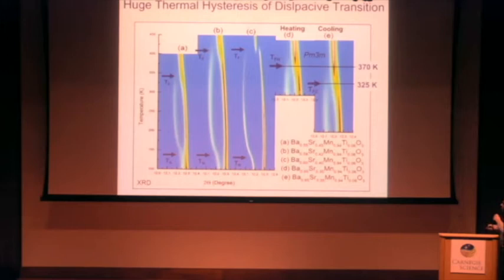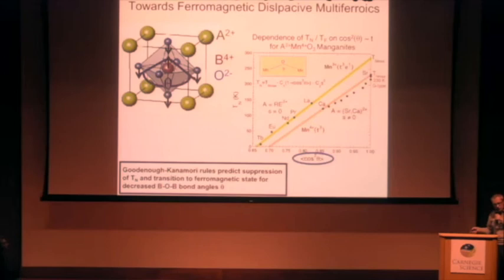Here is an example of several more X-ray diffraction experiments with many different samples. I want to point out this situation here with this composition, which we managed to measure both on heating and cooling. I want to emphasize this point: in this case, here is just cubic to tetragonal and then back to tetragonal or cubic at low temperature, so there are no three transitions. But this humongous hysteresis of this transition, which is now 45, goes up to 50 Kelvin. This is the problem with the measurement, because if you try to measure this material at high temperature, you remove some oxygen from the sample—very leaky behavior. And then on top of that, this humongous hysteresis. We do not have complete, except for the X-ray and neutron diffraction experiments, proof that they are ferroelectric.